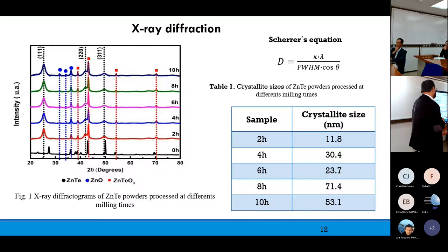pellets. As a result, we took the diffractograms of the zinc telluride powders processed at different milling times. We can observe that all of the diffractograms show the characteristic diffraction peaks for the zinc telluride zinc blende phase, with a preferential growth in the 111 plane. And other peaks can also be observed, referring to other phases such as zinc oxide